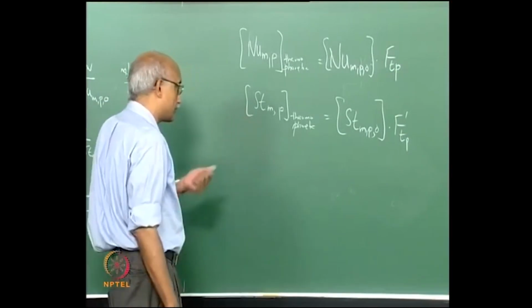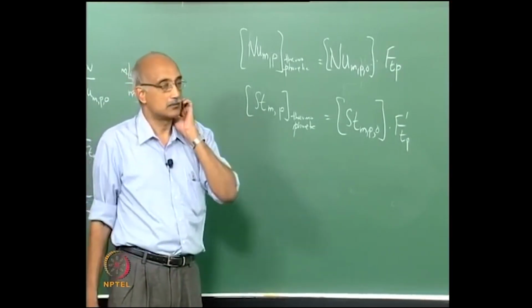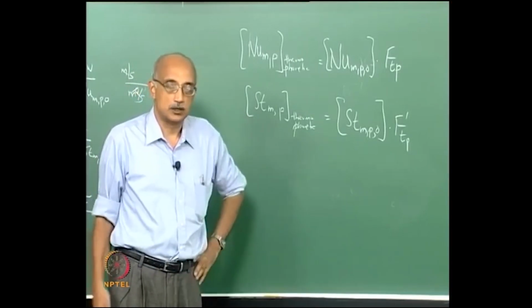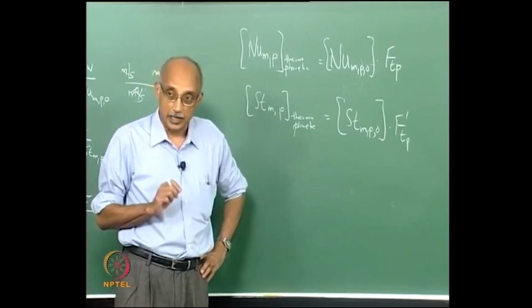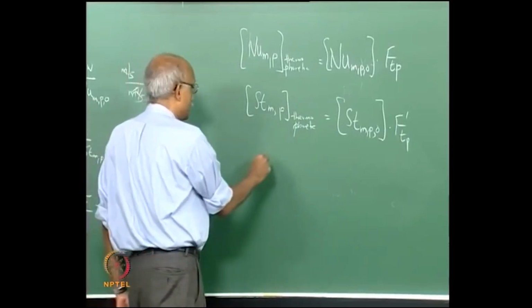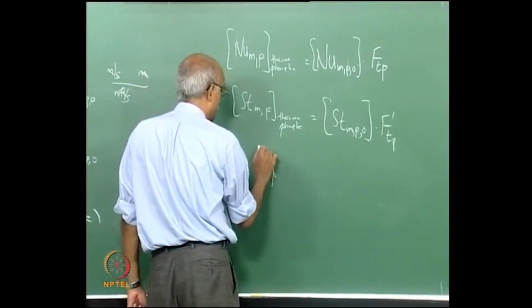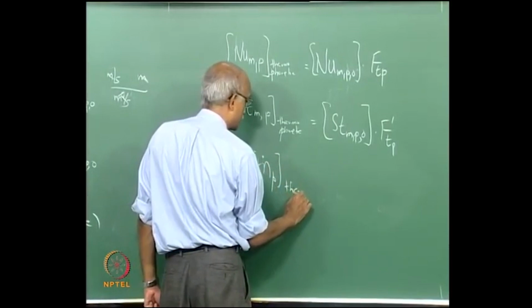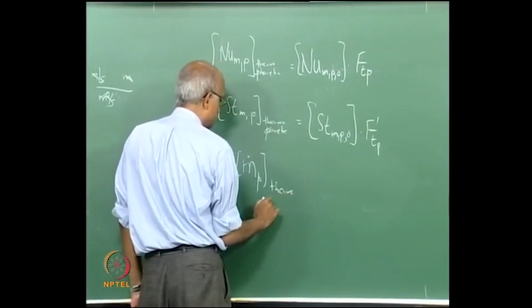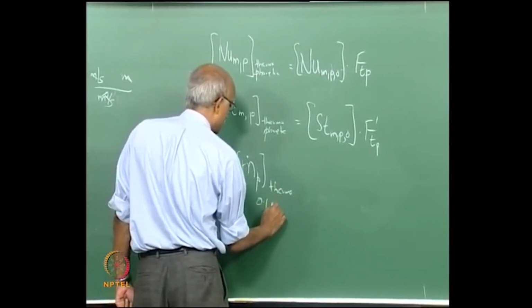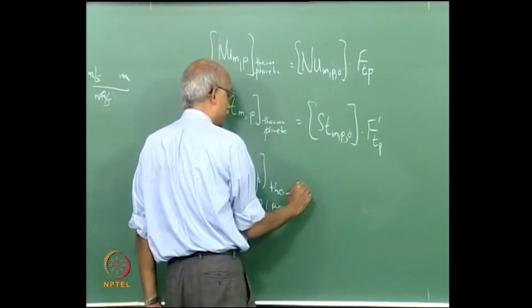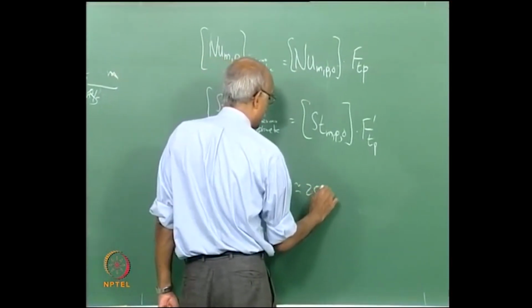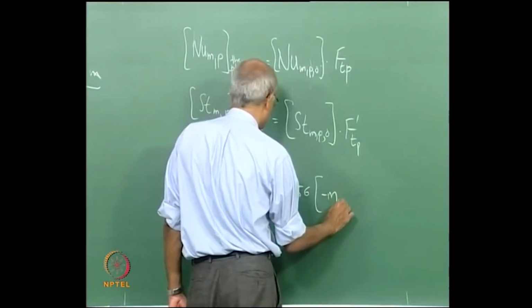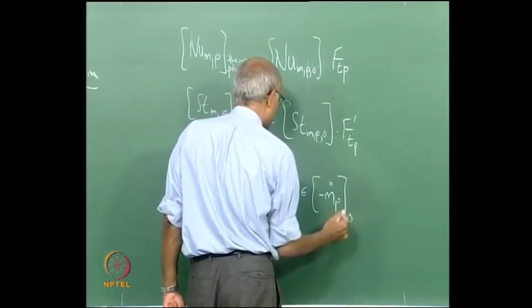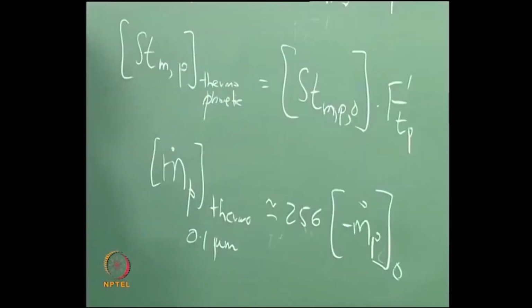So when you go through all that for the same problem for which we previously got 11 to 15 to 40 grams per year, now if you do the calculations, the mP dot value including thermophoresis for 0.1 micron sized particles is roughly 256 times what we had previously estimated without taking into account thermophoresis. So it makes a huge difference.